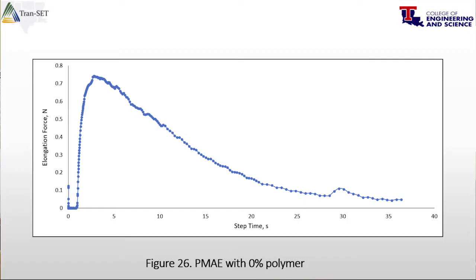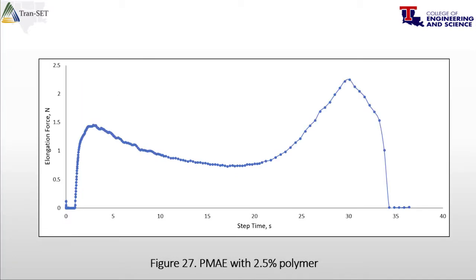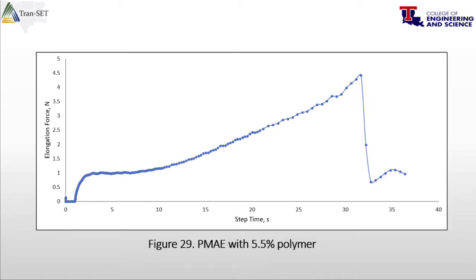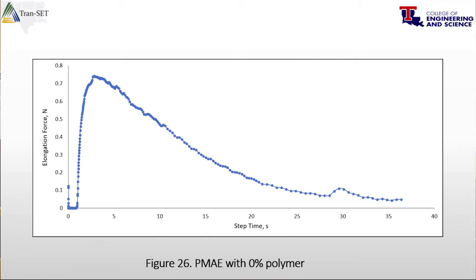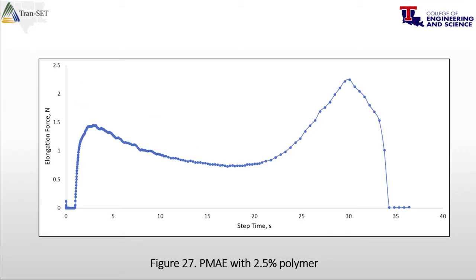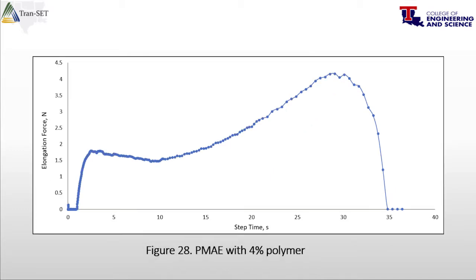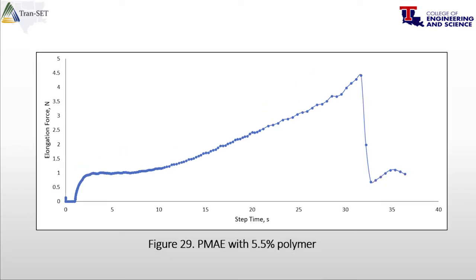So if you don't have any polymer, it looks like you just have one peak. Okay? If you have polymer, you have the second peak. So you see that this is the first peak, which comes from asphalt. This is the second peak, which comes from the polymer. Okay? So this is another result. This is for 0% polymer. This is for 2.5% polymer, so it increases. This is for 4% polymer, so it increased. And this is for 5.5% polymer.